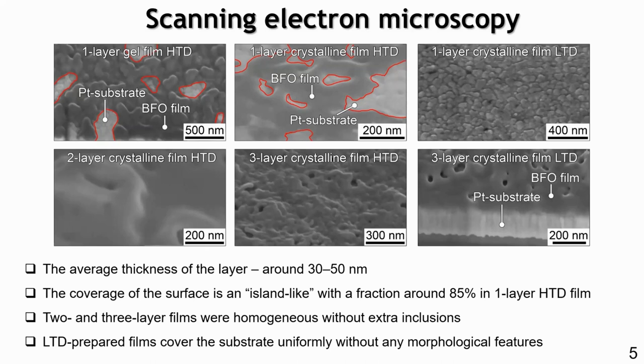You see that there are different regions with voids, and you may see the platinum substrate by the contrast in the backscatter electron microscopy. And that means that this film doesn't have a perfect coverage. And even after crystallization, so the second step, this imperfect coverage is conserved. In comparison, if you do long time and low temperature drying of the film, the coverage is absolutely perfect, so we don't see any platinum substrate.